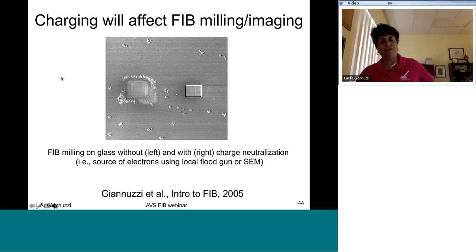Charging will also affect FIB milling as well as imaging. So here, if you've got a charging surface and try to FIB pattern on it, you can see that the charging surface can actually move the beam around. If you use a charge neutralizer, which is basically getting electrons down to the surface to neutralize this charge, you can then mill on features such as glass.